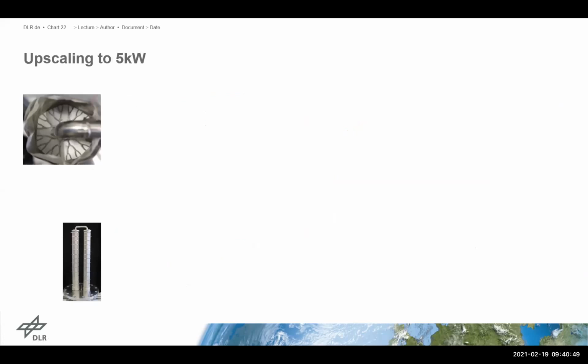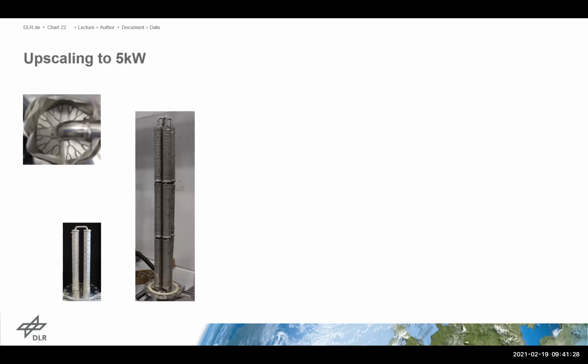One word regarding upscaling. This is the reactor we have shown you the results of. Normally, we have the problem with these thermochemical reactions that we have the heat transfer and the gas transfer, right? And this upscaling of these reactors is always a bit tricky. Either you improve the heat transfer or the gas transfer, so they are normally not independent from each other. The concept behind this storage principle is that we only have the gas transfer in radial direction here, so we can make longer tubes and we can have more tubes. The gas itself is distributed pretty easily inside of the shell. Okay. And this is what we have investigated.